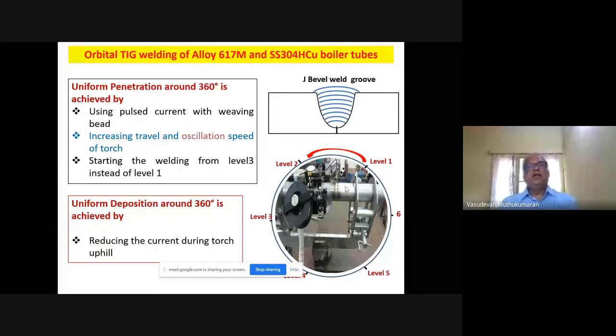You can see here a welded component. We got a root side uniform penetration. Cross section you can see. The wall thickness was 11.9 mm. Tube OD was 52 mm. It required around 11 passes. The fabricated tube qualified radiography and liquid penetrant testing. See the cross sections here.